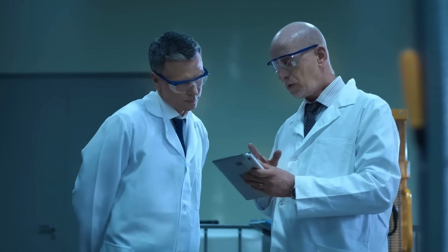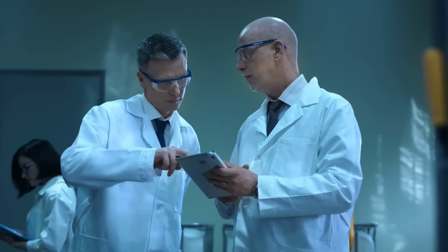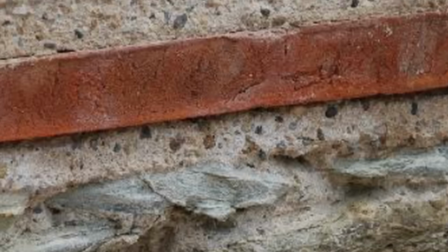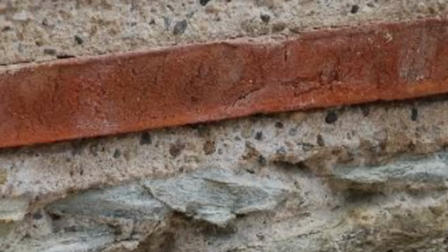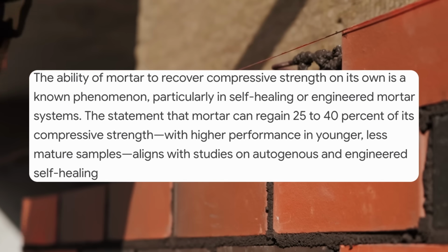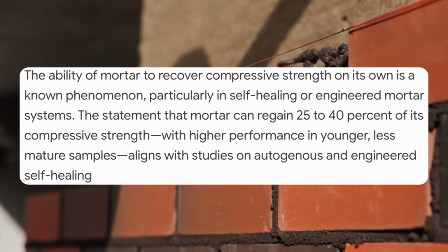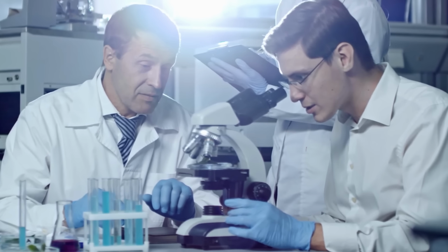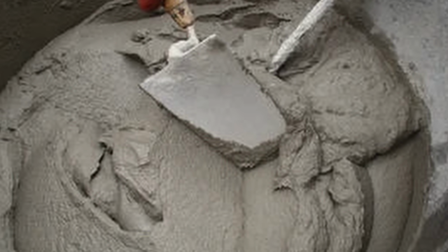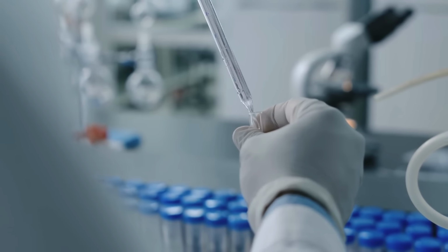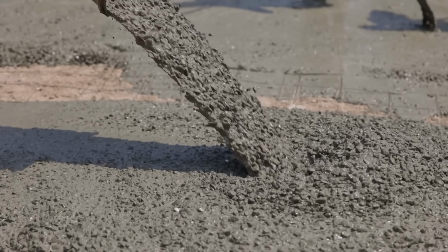A research team led by Nardi, publishing in the journal Composites Part B, tested this exact process in a laboratory. They damaged lime mortar specimens, let them heal, and then measured what happened. The mortar recovered between 25 and 40% of its compressive strength on its own, with the youngest samples healing most aggressively. The researchers called it autogenous healing, the mortar doing it with no human intervention, no additives, no repair work, just chemistry and time. Now look at modern concrete.